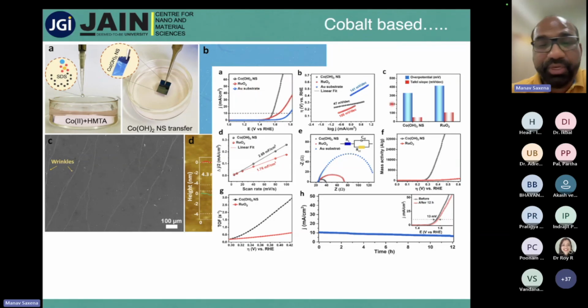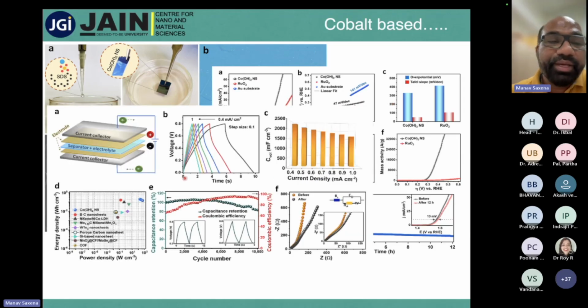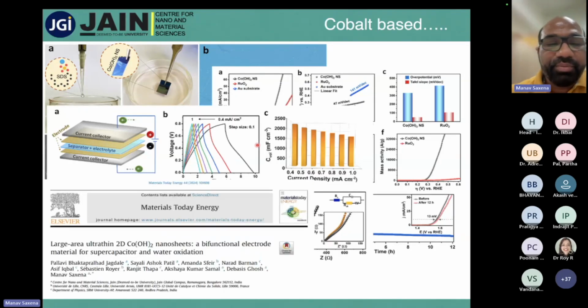We have done the complete study, and we have also made a device with a current collector. It is a symmetric device, and we used a separator and electrolyte. It is stable up to 10,000 charge discharge cycles. Because the material is around 4 nanometers thin, it is also a flexible device. We have done all the catalyst study, and we published it earlier in Materials Today Energy.